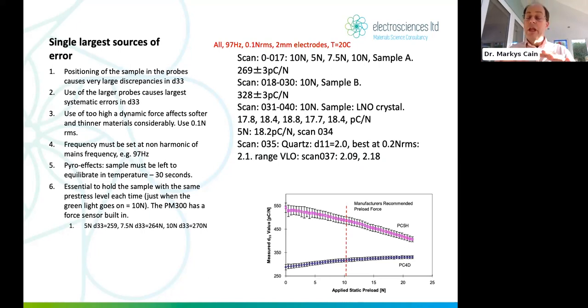Use of too high a dynamic force. We apply a static preload, maybe a Newton, maybe 2 or 3 Newtons, to hold it in place. That's important. But also the dynamic force, the small oscillatory force we use to excite it piezoelectrically, that we then measure the piezo charge response. That's important. We mustn't use too high a stress, because a lot of these materials, especially soft PZT and polymers, are very thin materials. The materials have an inherent response to force, and it's not always linear. The nonlinear response in a soft material, or a higher stress than you might expect from a point contact, can actually depole locally the softer material underneath the probe. Even though the load is only a few newtons, the stress can be really high. So you've got that issue to deal with as well, which is why 0.1 Newton RMS is the recommended good practice here.